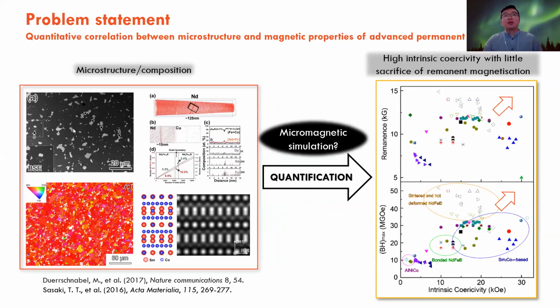Previous research has used broad microscopies to look at the microstructures from the microscale to the nanoscale, or even the atomic scale, to get the composition, the defects, and the different phase fractions. And the way they correlate the microstructure and the magnetic properties is by using micromagnetic simulations. But the quantification here is actually not that quantified, because they usually use default values as input for their micromagnetic simulations. Even when they have some features and some information, they didn't transform the observations into information as the input for their simulations.